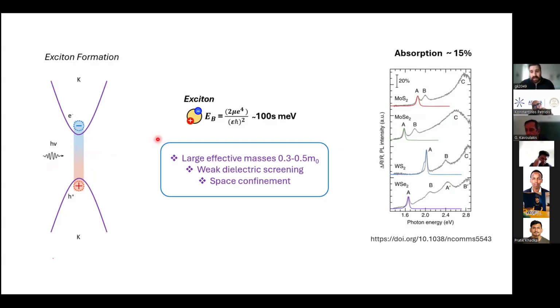Now, the important and interesting thing in the TMD group is that the excitons of two-dimensional thickness have very large binding energies. They are very stable, very robust. The binding energies are on the order of hundreds of millielectronvolts. And this is owing to the large effective mass, the very weak dielectric screening because of the absence of extra layers, and the space confinement. If we compare these binding energies to classic semiconductors like gallium arsenide, they are an order of magnitude higher. This is why in gallium arsenide, it's very hard to observe PL emission at room temperature, whereas here we can observe PL emission at room temperature, because the thermal energy at room temperature is around 30 millielectronvolts.